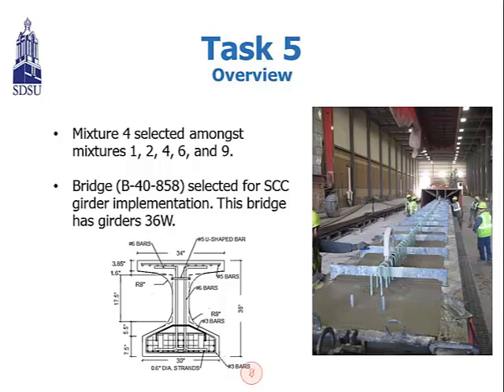After that, we must choose the one most promising mixture to cause the worst scenario, which is having the substantial prestress losses. So we chose mixture four among the mixtures 1, 2, 4, 6, 9, and then we used mixture four to fabricate the bridge girder. As you can see the details for the bridge girder, and you can see the picture when we completed pouring the SCC concrete in the girder.